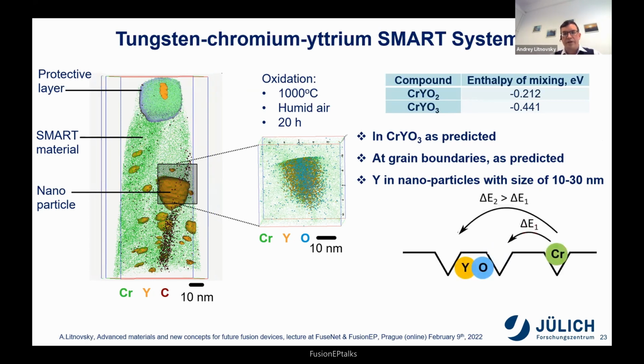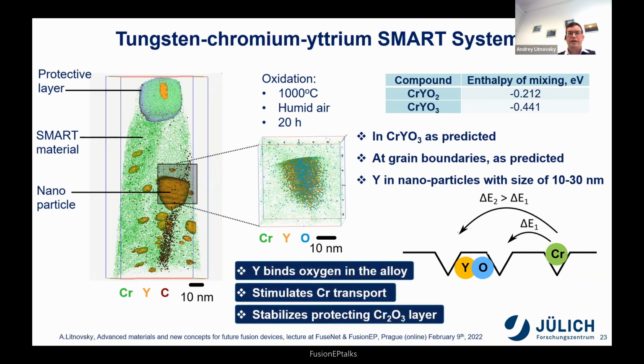What else does the yttrium do? Yttrium, as we see, binds oxygen. So the chromium can move further without any obstacles to form this protecting layer to protect tungsten from oxidation and sublimation. And thus it stimulates the chromium transport. So the effect of the yttrium is fantastic in these conditions. And this is, as you see, a highly nano material.